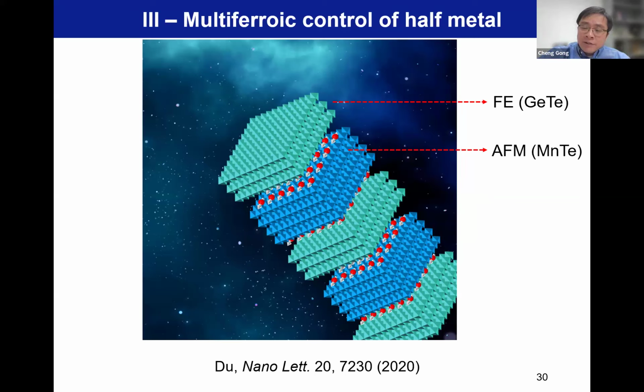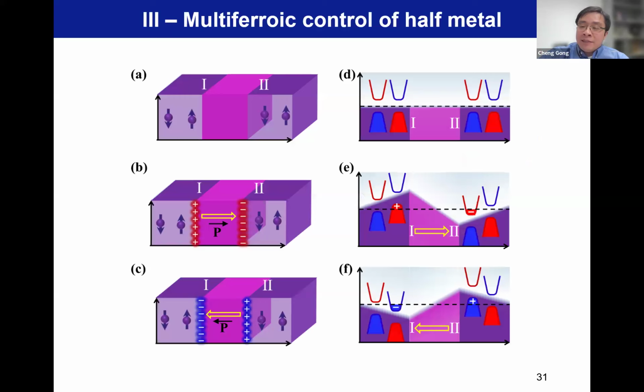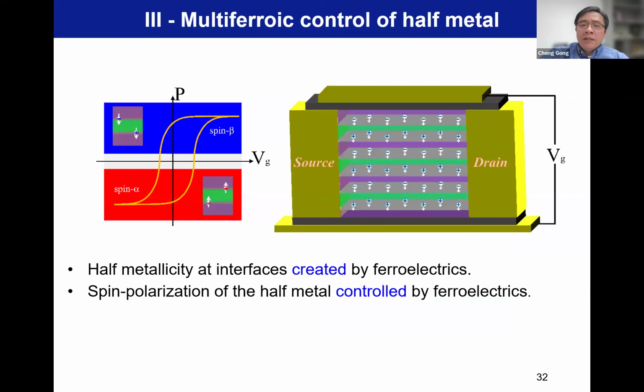You use ferroelectric to control an A-type antiferromagnet. Again, you have a similar band alignment as I just showed in the second part of the work, a ferroelectric polarization-dependent band alignment. You can push the spin up or spin down band to the Fermi level. So to realize half metal, in the end, you can build such a multiferroic field effect transistor.